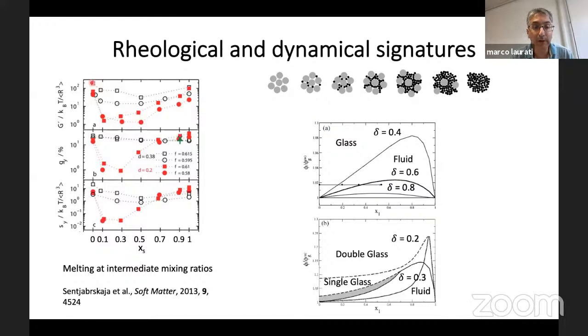So as you can see here, the signatures that we could see were evident in, for example, the storage modulus of the mixtures, but also the yield strain and the yield stress of our systems. As you can see, for a large size ratio of 0.2, where the big particles are 5 times larger than the small particles, we could see that there is clearly a minimum in all these three quantities at a certain intermediate ratio. Which is, of course, an indication of a transition, at least from a glass state to a more fluid state, which is consistent with the expectation of the theory that Magdalena was developing.